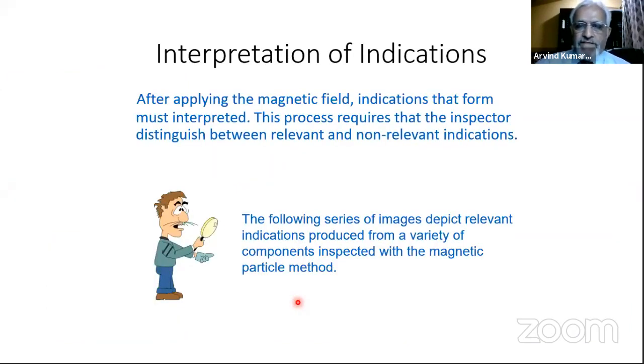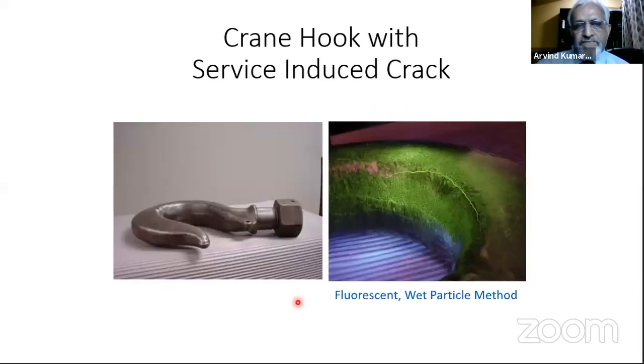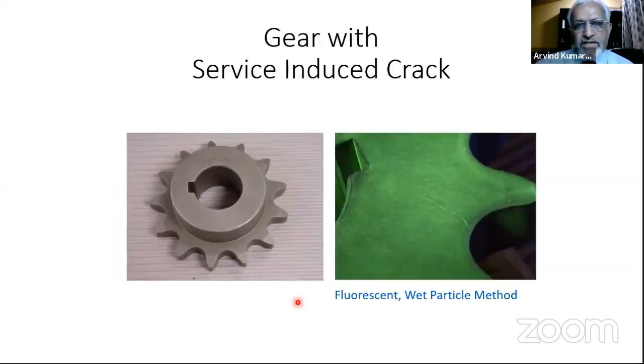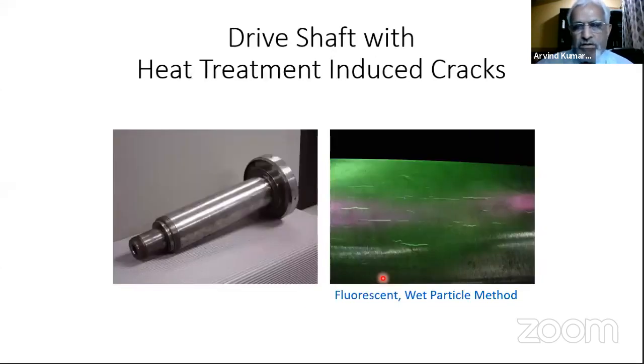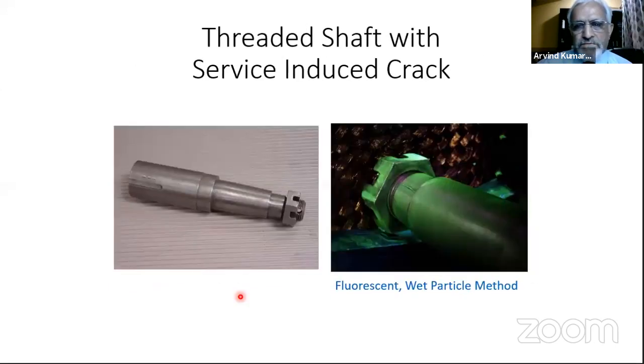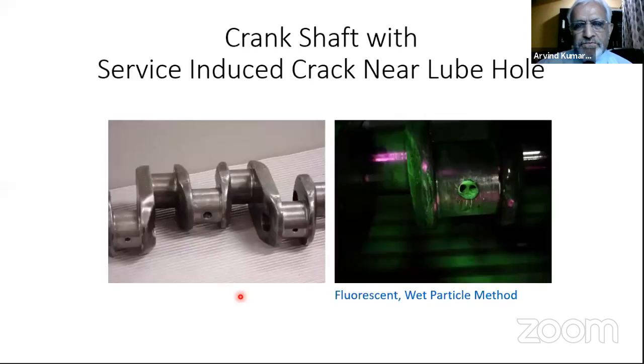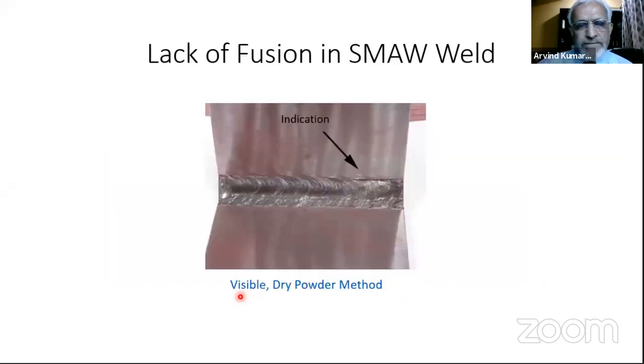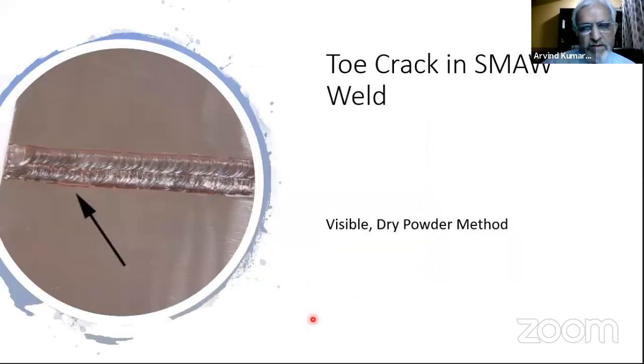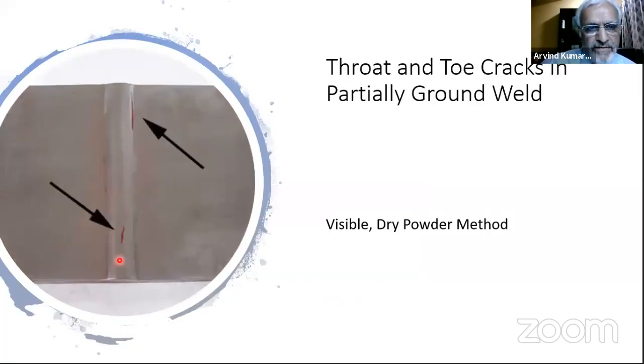Now, seeing the indications which are formed, all these are using a fluorescent method. In the shaft tested with fluorescent, and this gear tested with fluorescent, you can see a crack here. Again, very clearly you can see under UV light the indication that is formed. On the weld, on the edges, you can see there is lack of fusion in an SMAW weld. There is manual welding. Here also you can see there is a toe crack, and there are some undercuts also, which you can see on this other side. Again, there are cracks at the throat and toe of the weld.